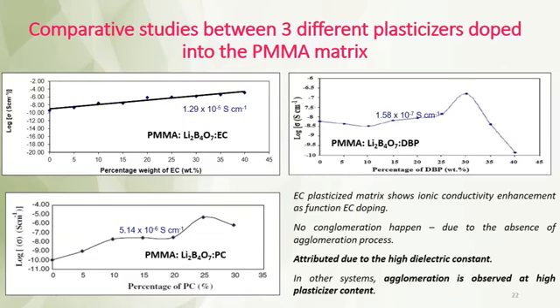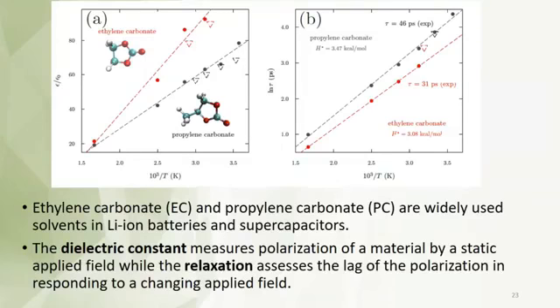We can see from here, plasticizers generally can increase the ionic conductivity of the polymers, attributed to the high dielectric constant of the plasticizers itself. But we can also see at high concentration of the plasticizers, agglomeration can be observed and the conductivity can decrease. So the formulation of the right weight ratio of the plasticizers is crucial in any studies. And ethylene carbonate and propylene carbonate are widely used plasticizers. This is due to their dielectric properties, and the dielectric properties are also shown in the graphs above.